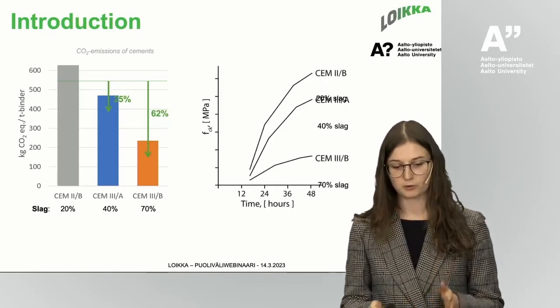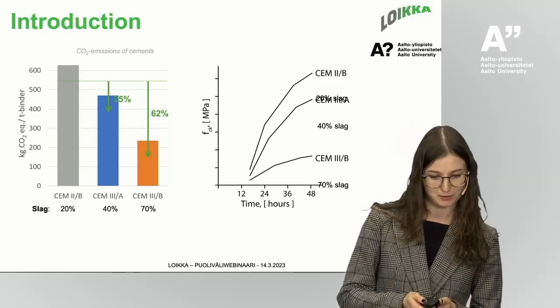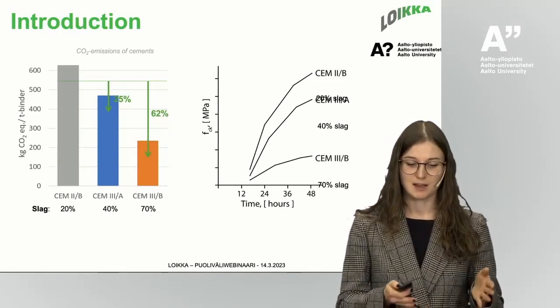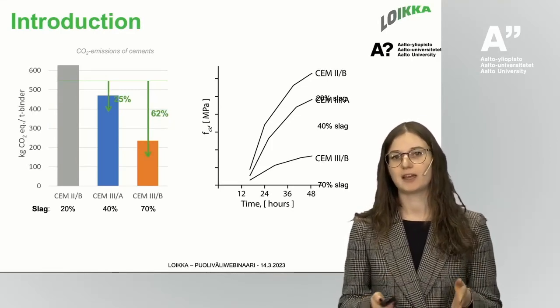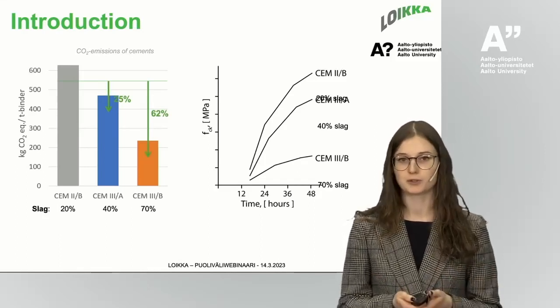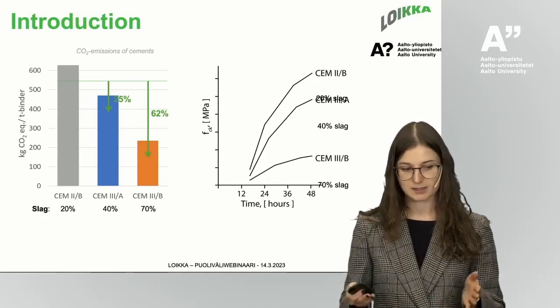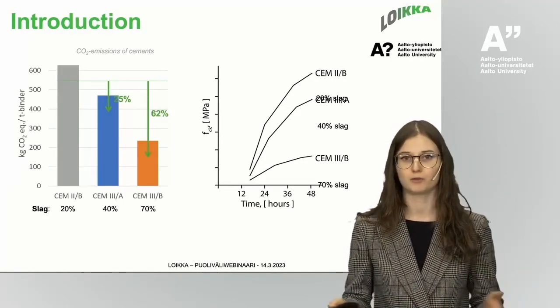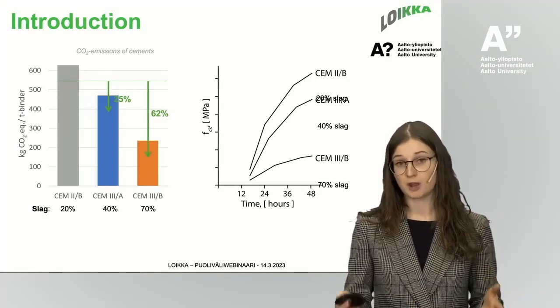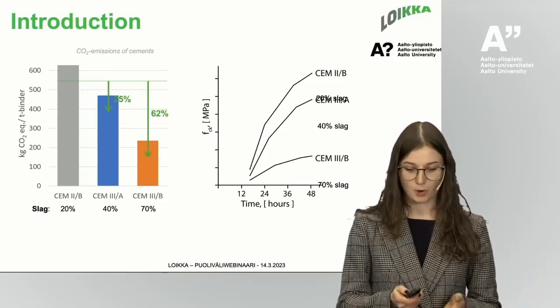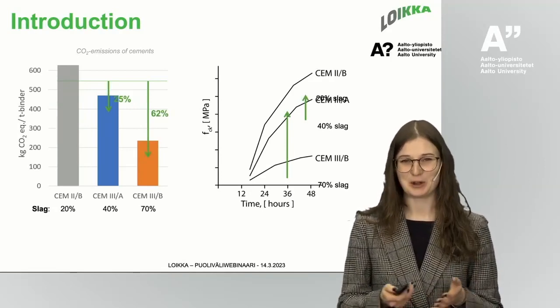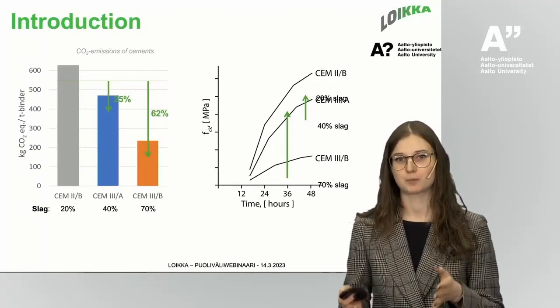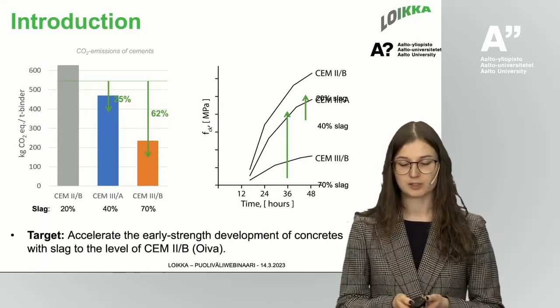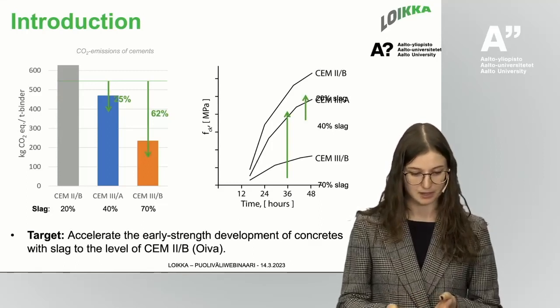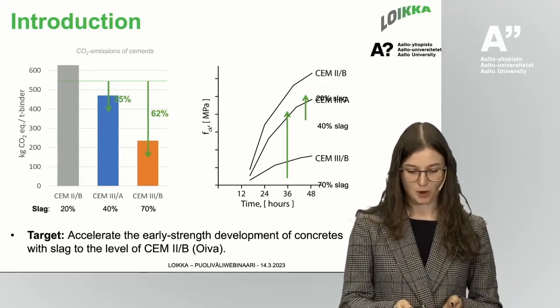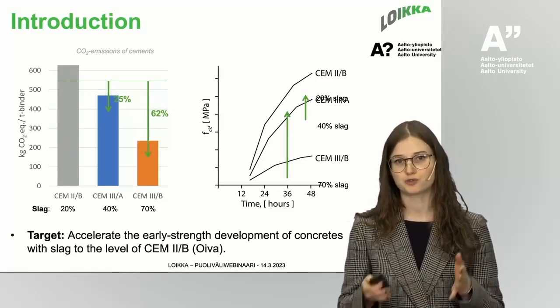One problem with concrete that has a lot of slag in its content, I'm sorry about some shifts in the text on the graph, is that when you have a lot of slag, the compressive strength at early ages is reduced compared to, for example, CEM 2B. And this is actually postponing the whole timetable of the construction site, and for example, the frameworks will be removed later. So our aim is to accelerate the early strength development of concretes with cementitious binders that contain a high amount of slag to the levels of CEM 2A and B cements.